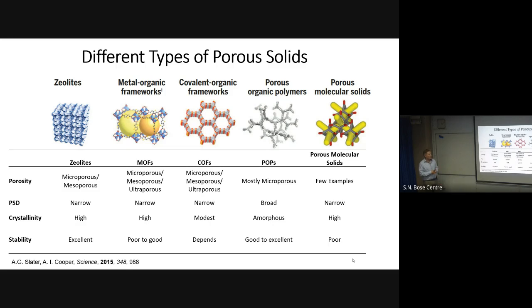Then you have porous organic polymers. Some people say that you call your porous material a porous organic polymer if you are unable to crystallize it, because this is kind of the major difference. So it's often a non-crystalline organic framework. They are mostly amorphous. You usually have micropore systems. The pore size distribution is quite broad, though, but the stability is different from the frameworks: they usually have quite strong bonds, so you use Suzuki couplings or similar very fast reactions that form stable bonds.